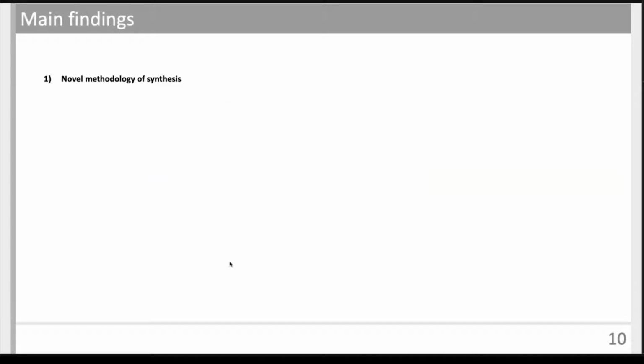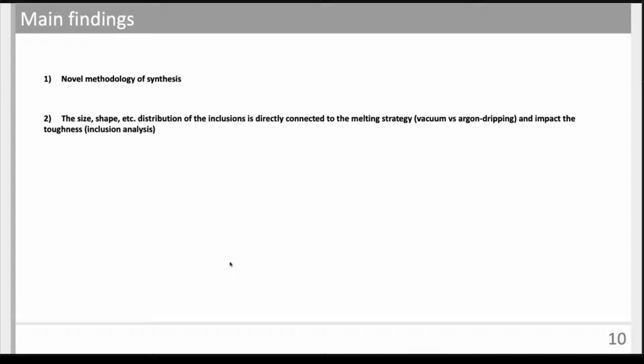First, we were able to verify that this novel strategy to pollute the melt with oxygen using hematite, and further mimic a commercial alloy by deoxidizing it with aluminum, was representative. We could check that by validating the size, shape, morphology, and also distribution of the inclusions. And we could see that they are directly connected to the melting process, which in our study was linked to the atmosphere of the furnace, like the vacuum and the argon dripping. And we could see that these inclusions impact the toughness.